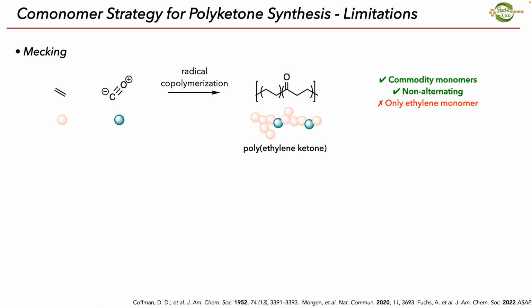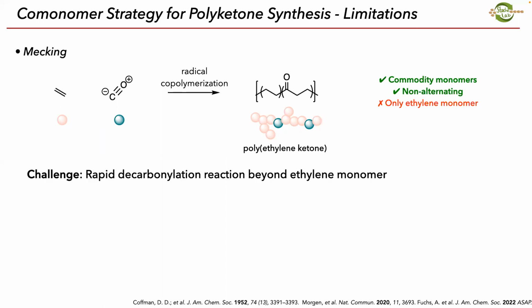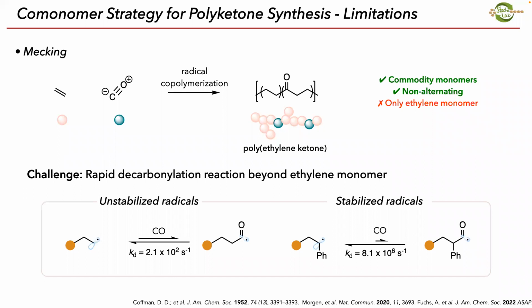The challenge is it only works for ethylene. So ethylene is the only monomer that this strategy will work with. And the reason being, not to get into too many technical details, but in a radical copolymerization, if this reacts with carbon monoxide, it will generate an acyl radical, which can undergo a reverse reaction. So this is in an equilibrium. And so we need a high pressure of CO to drive this forward so that we can put this ketone into the backbone. So this is great for ethylene, and we can drive this process forward.